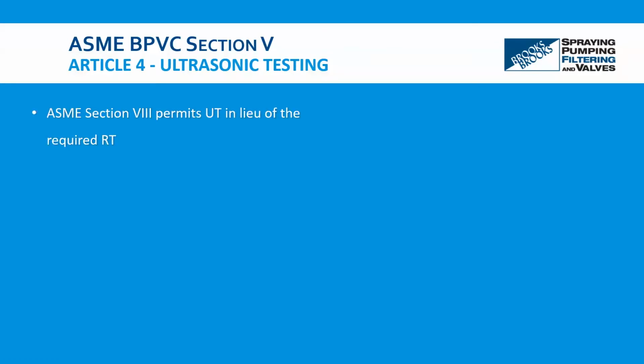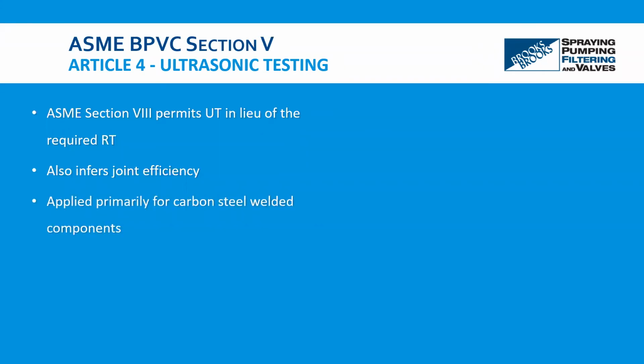On to the next type of NDE, which is ultrasonic testing. It's similar to radiography in the sense that the requirement for ultrasonic testing is governed by the same section, again UW-11. It fulfills a similar purpose as radiography in that it's used to detect internal defects and measure material thickness. Ultrasonic testing may also be employed to confirm the joint efficiency of the joint. Now, a caveat is that it may be difficult to implement on a stainless steel vessel, because whenever the ultrasound encounters stainless steel material, it encounters severe attenuation, and that could lead to incorrect readings. That's why it's preferred for carbon steel.